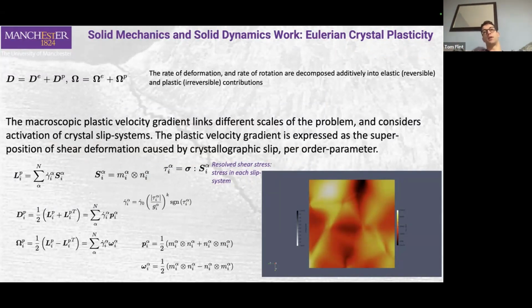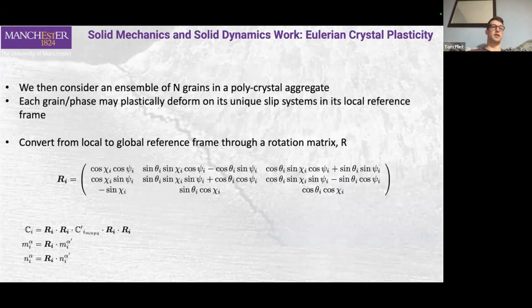So there are many crystal plasticity approaches out there. They're all Lagrangian, and they're all only applicable at low to moderate strain rates. If you want to look at really high strain rate systems, then you need this Eulerian approach, which we've developed in the last few months. It's much more complicated in certain ways than the Lagrangian approach, because now you have to advect all these fields through your computational domain, which is expensive. But we found novel ways to do that.